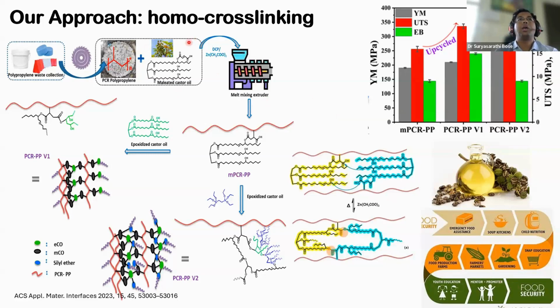So we took this oil and we made a lot of derivatives of this oil, for example, epoxidized, or you can introduce some maleated groups and so on. So this is the post-consumer recycled polyolefins, which we sourced. They come in the form of chips. So you take this, you mix this oil, and you add certain agents in an extruder, and you form a compound.